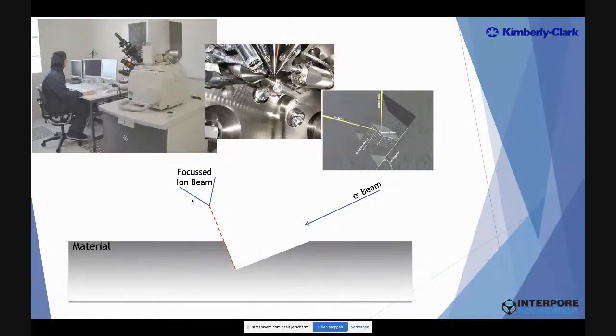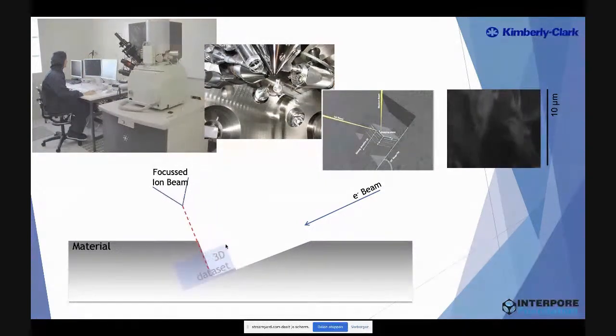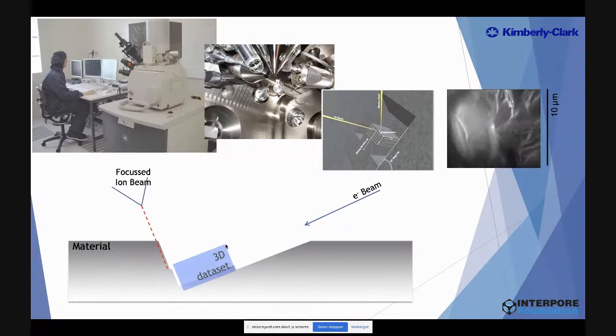One of those techniques, for instance, is focused ion beam scanning electron microscopy. With this technique, with the focused ion beam, you etch a little bit of your material away, and then you take an image with a scanning electron microscope. And this allows you to take a series of images by etching some material away. So you get a 3D data set, but it is in a destructive way. So to image dynamic pore-scale processes, that is not the way to do so, but it allows you to get a detailed 3D representation of a small volume of your rock.